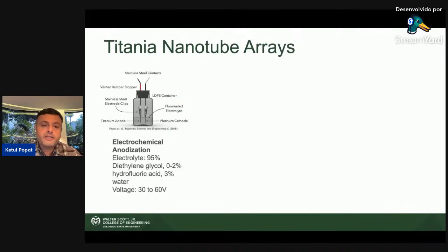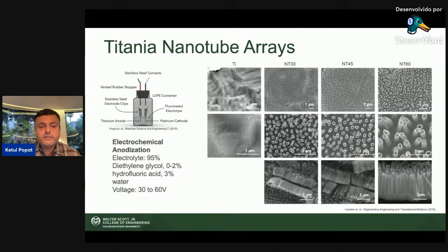And for many years, we have used a very simple technique called anodization. This is a technique where we take titanium and anodize the titanium in an electrolyte using a cathode. We use platinum as a cathode, and we can do some really interesting things. So you have a titanium surface, very plain. You can see grain boundaries and things like that. But when you start doing this anodization process, you start seeing these kinds of surfaces. These are not deposited; these are growing from the surface. So you grow these kinds of nanotube structures from the surface.